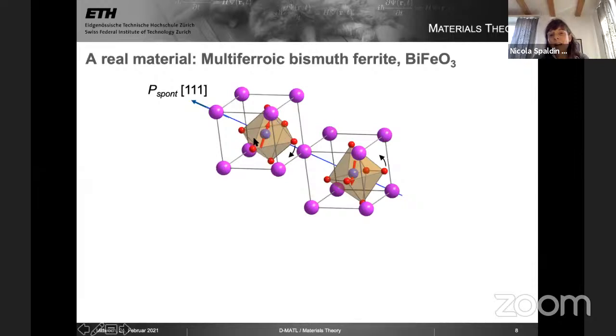And these iron ions are magnetic, of course. They have 5 3d electrons, so they have a very large magnetic moment, and they're antiferromagnetically coupled to each other by the usual superexchange through the oxygen. They have a small net magnetic moment because the moments cant a little bit. The bismuth ions, it's 3+ trivalent bismuth, which has a very strong stereochemically active lone pair of electrons.